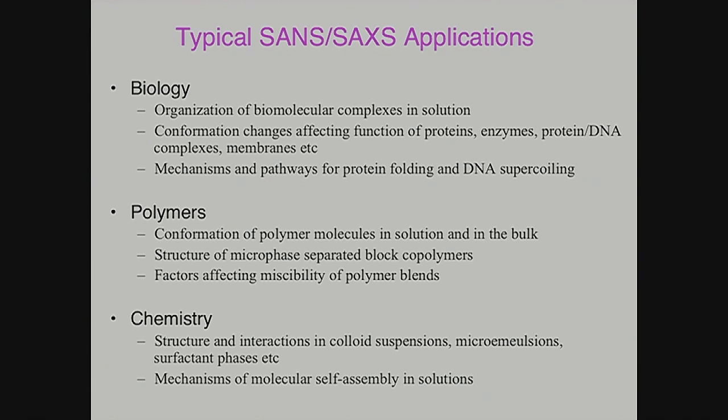So they were able then to measure what's called the radius of gyration of the polymer, and to figure out how it scaled with the number of monomers in the polymer. Any of you who know about polymers know that there are various different scaling exponents which had been proposed before they were actually measured for this radius of gyration. So that was one of the first big impact neutron scattering experiments, SANS, small angle neutron scattering experiments, in the polymer field.